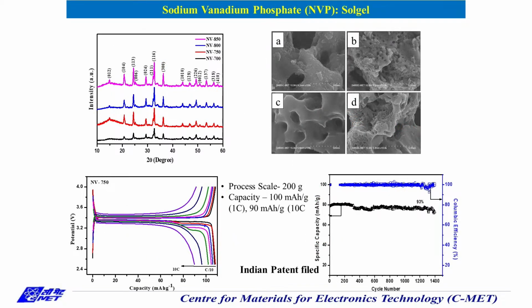You can see that there is another product we have developed, sodium vanadium phosphate. It is highly porous. Because of this porosity, we get good ion transport and good capacity, almost 100 milliampere hour per gram. It is very close to a lithium ion battery. So now our sodium ion battery development is very close to lithium ion battery. Maybe within 3-4 months we may come out with a good sodium ion battery technology.